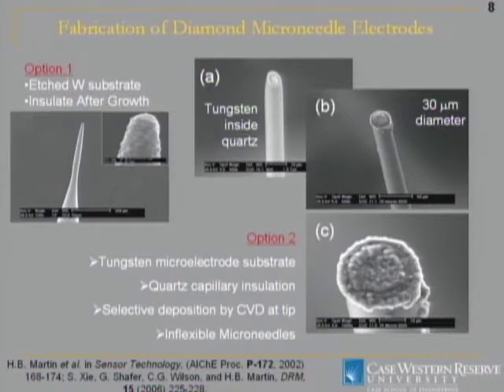And then we put it into our CVD diamond reactor, and we can grow diamonds selectively at the tip. This is a 30 to 35 micron diameter disc electrode. Again, it's polycrystalline, as I mentioned earlier, and you coat it on various materials. These are inflexible microneedle electrodes, so I'm not aiming to make them flexible to go in tissue yet, although we were hoping they would still work in tissue.